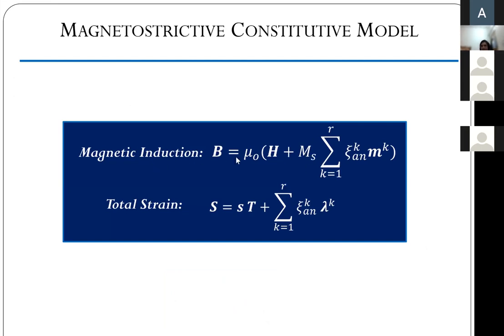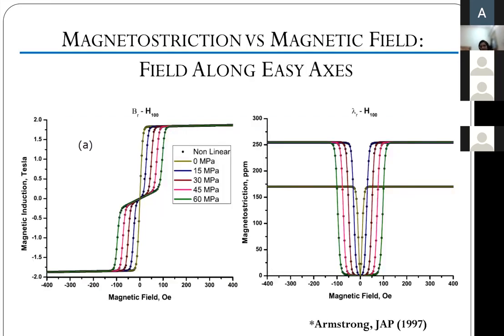And then we calculate magnetic induction, which is nothing but mu naught times H plus M. That's a universal equation. Then similarly, total strain, S is the compliance matrix. Interestingly, here the mechanical response is linear. If there was no magnetic field, stress versus strain behavior is linear, strains are infinitesimal, and all of that still works. The second term is the magnetostriction. Again, this depends on magnetization. Once we solve for M_k, we get lambda_k within the domain, and then we sum up again using Boltzmann averaging.